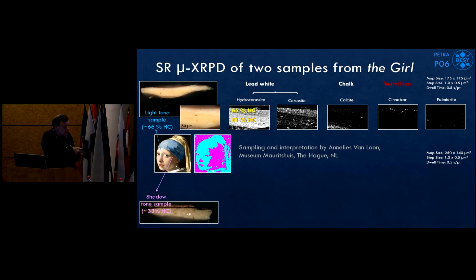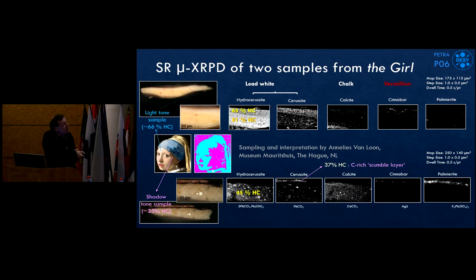And for instance, here the sample from the upper layer shows actually optically maybe a small distinction. Also a distinction in hydrocerussite content, which is just a distinction between the base and the ground layer and what's on top. So nothing really special. And that's what we expected also from the macro scanning. But here you see that there is another stratigraphy. There is a thin layer on top, and the thin layer has quite a different hydrocerussite content, which we now call the scumble layer, than what is below.